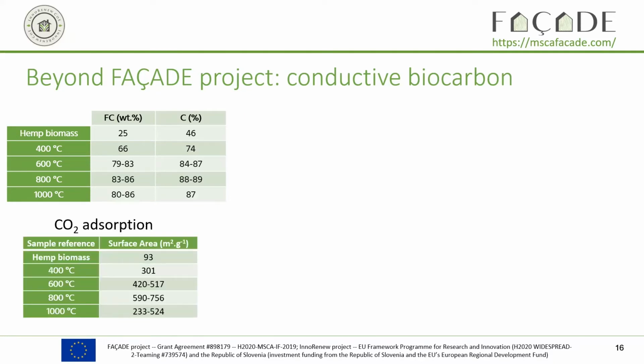Then we looked at the CO2 adsorption. So the CO2 adsorption provides information about the microporosity of the sample. So we saw that the microporosity is increasing up to 800 degrees, and then it is decreasing at 1000 degrees. We related this microporosity to the volatile matter that is going away from the sample when we carbonize it.